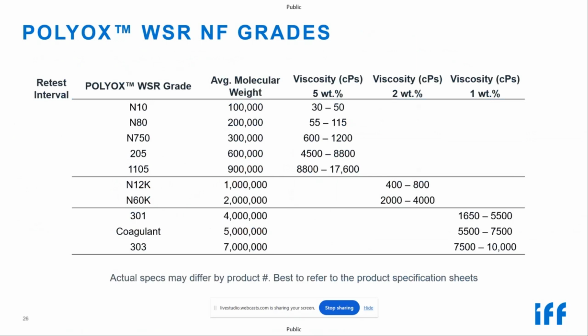The similar chain scission rate, but the difference in the impact on observed solution viscosity, impacts our retest intervals for polyethylene oxide. For our lowest molecular weights, N80 and N10, we have a 2-year retest interval. It doesn't affect the viscosity as much as the higher molecular weights, so we can have a longer retest interval. For the bulk of the middle grades, we have a 1-year retest interval. And for our very highest molecular weights, coagulant and 301 or 303, we only have a 6-month retest interval.